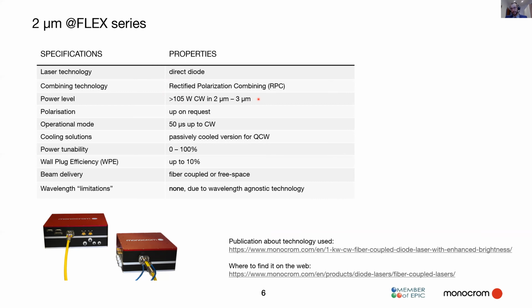Since it's laser bar based, so semiconductor based systems, we can have pulsed conditions up to 50 microseconds, 10 kilohertz or more, depending on the electronics that you are using. And we also can operate the systems in CW. Due to the semiconductor materials and the electronics used, we can have a power tunability from 0 to 100%, and we can achieve wall plug efficiencies up to 10% in this wavelength region. Besides delivering these systems fiber coupled, we can also deliver them as free space versions. So if your application requires a certain degree of polarization, we would skip the fiber coupling and can restore the polarization orientation with our beam combining technology.